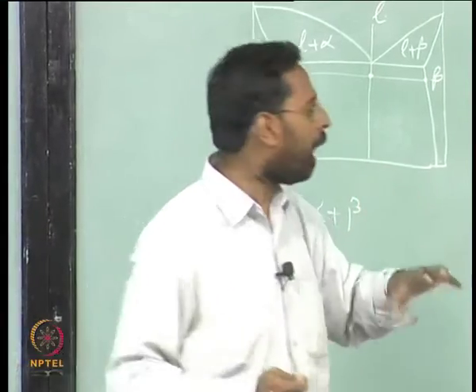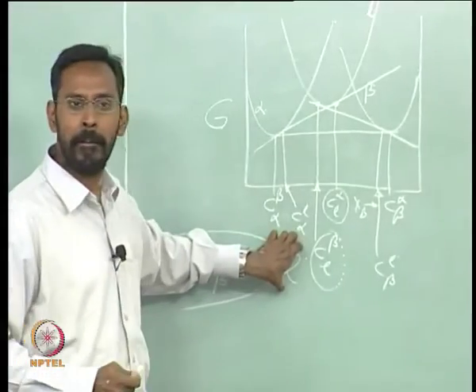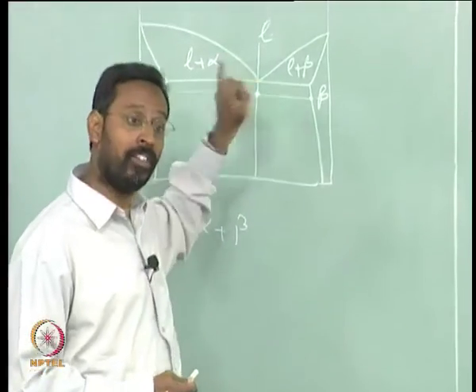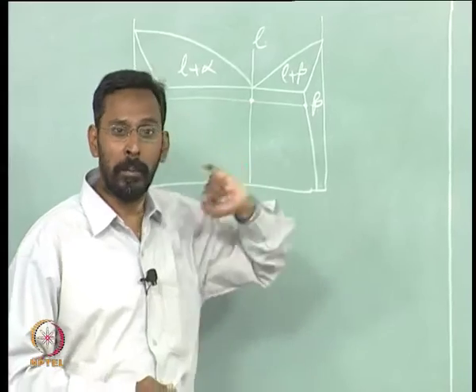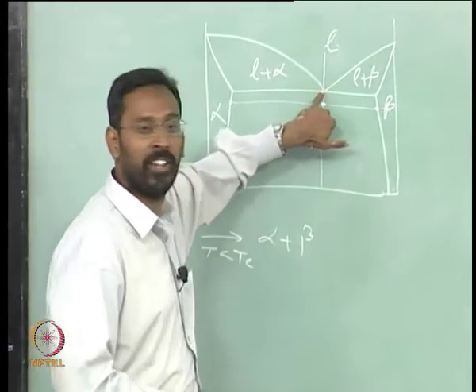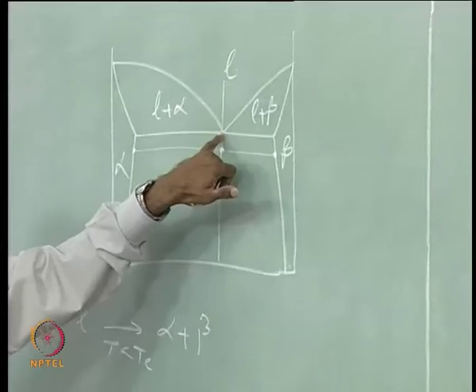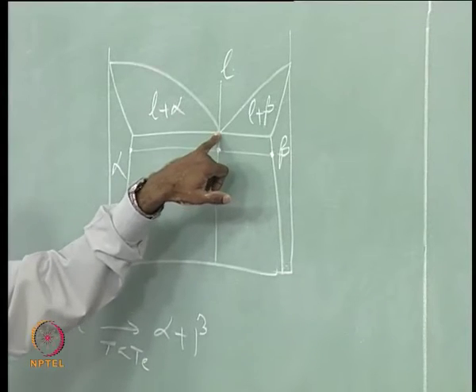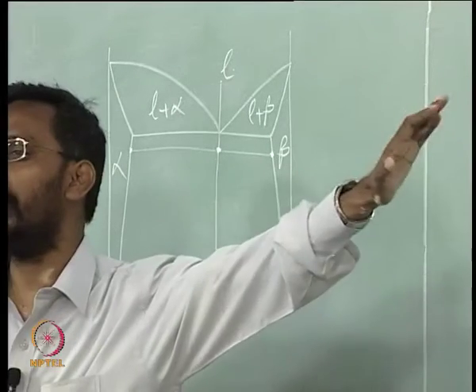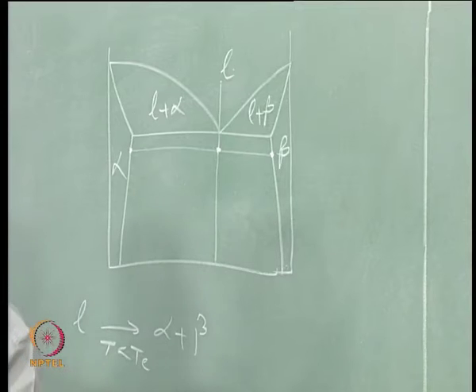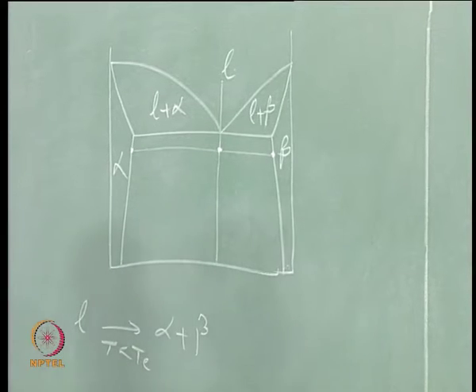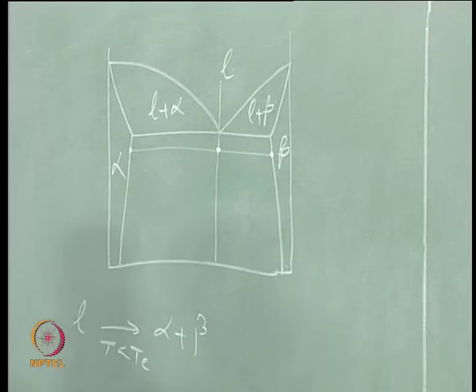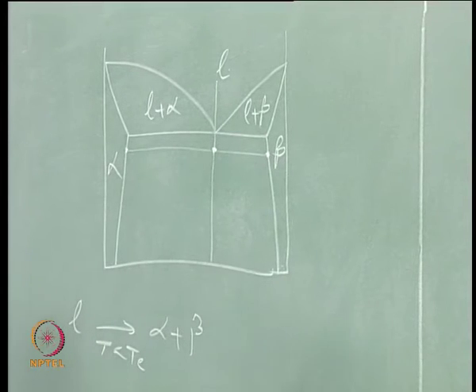If alpha and beta have to exist with the liquid, the only way that is possible is at this temperature we are talking about. Remember, at the eutectic temperature it is the same because it is a common tangent between all three, but we are talking of a temperature below the eutectic. I have brought the liquid below the eutectic and now looking at what would happen.